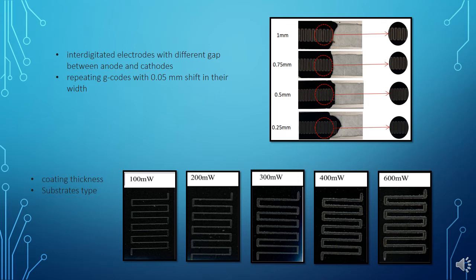As mentioned before, the laser power and the speed are parameters that must be optimized depending on the electrodes and their applications. The parameters are dependent on the coating thickness and substrate type of the electrodes. In this study, glass substrates were used, which were coated with electrode materials. We can see pictures of electrodes that were patterned with various laser powers. The power levels used in this study were set to 100, 200, 300, 400, and 600 milliwatt.